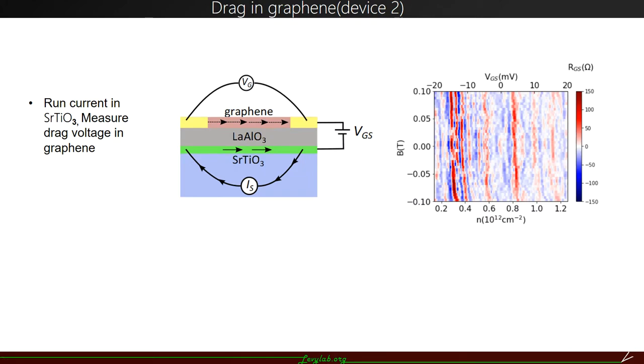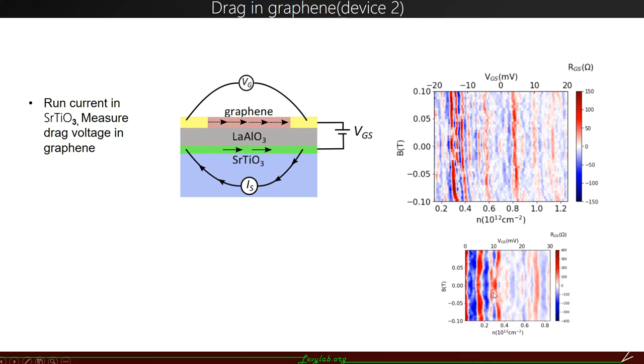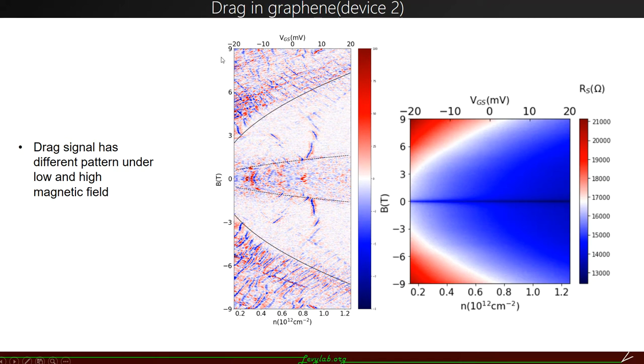Then we try to study the drag signal in graphene in a much larger magnetic field region. So in device 2, we still got the stripe-like features, which is very similar to the first device, and then we scan the signal in a much larger magnetic field up to 9 Tesla, and we can see these two parabolic shapes of the outline of the drag signal. So we can see the signal is more obvious in the high magnetic field region and low magnetic field region, but not in the intermediate magnetic field.